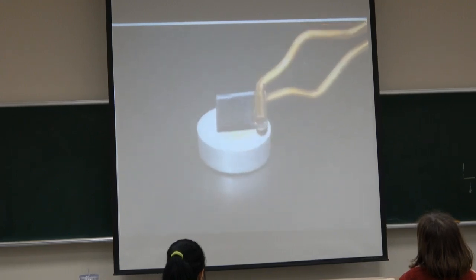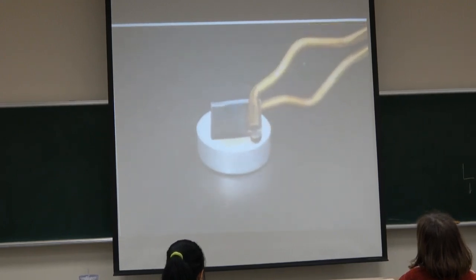Step 4. Place the carbon-coated slide face up on the counter. Be careful, the slide will be hot. Allow it to cool. Then, use a tissue and cotton swab to clean any residual soot off the edge of the slide covered by the metal tongs to clear the carbon off a 4mm strip. This edge will be where the alligator clip attaches. Step 5. You have now made a carbon-coated counter electrode. The carbon coating on the slide is very fragile and is easily rubbed off. Be careful not to touch it.